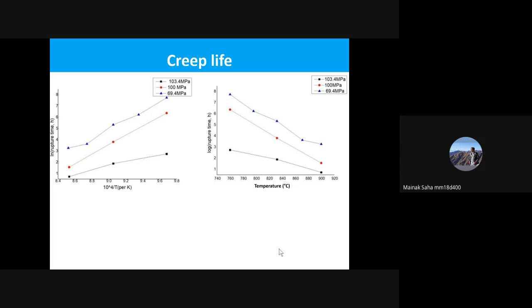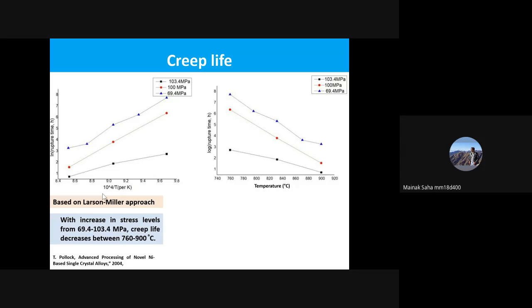Right? So in that case, there are two very common approaches. The first is the Larson-Miller parameter approach, where we plot the rupture time in hours on a logarithmic scale as a function of 1 by T. I have taken 10 to the power 4 just to scale these values up, otherwise they would come out as decimals. So it is 10 to the power 4 by T, where T is in Kelvin, so this becomes per Kelvin. What we observe is that with an increase in stress levels from 69.4 to 103.4 MPa, the creep life decreases between 760 and 900 degrees centigrade.